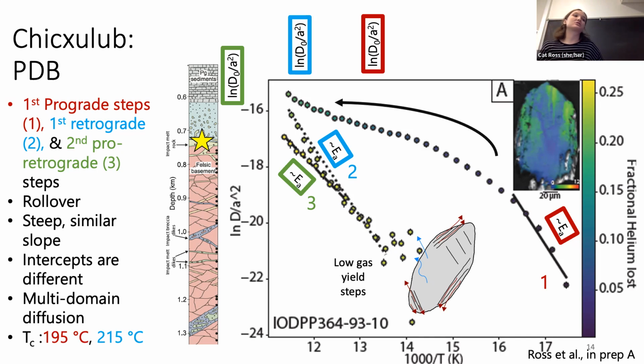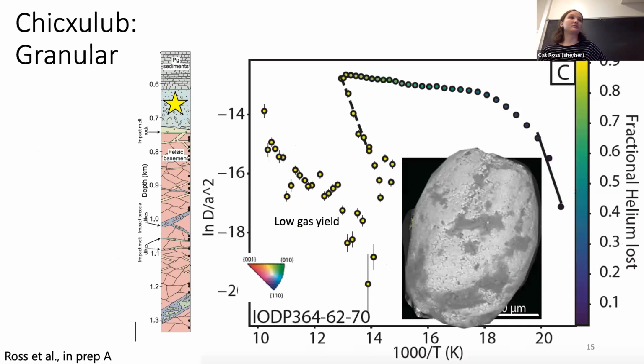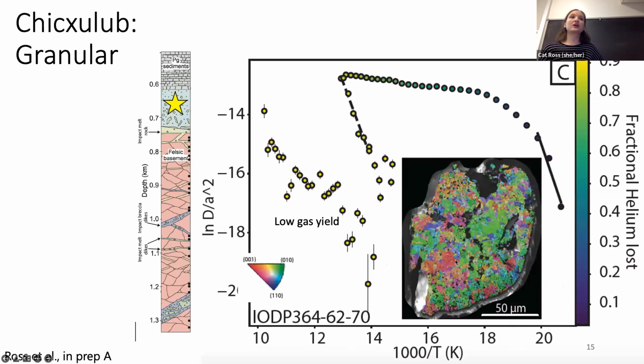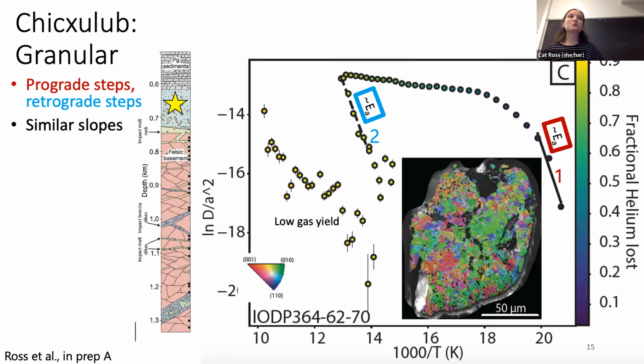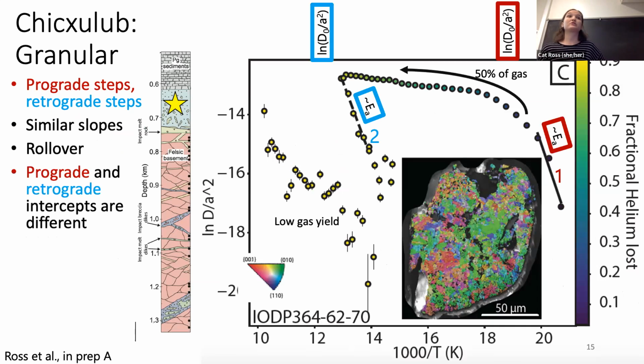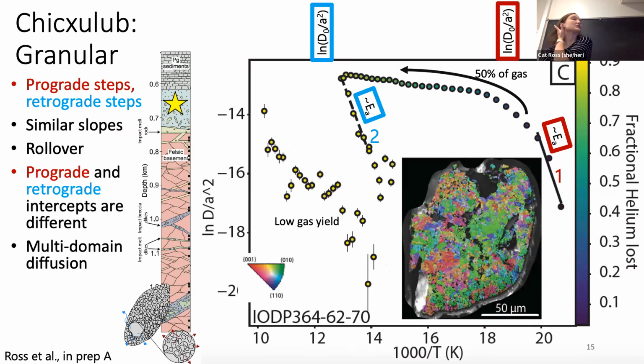And our closure temperatures are again within that accepted range. Finally, this granular textured grain, these beautiful tiny little granules in a single zircon crystal, yields 2 best fit lines, similar slopes with a rollover in between, but 2 very different y-intercepts. So again, this is indicative of multi-domain diffusion. And here we get a closure temperature that's much lower than that 200 degrees Celsius mark.